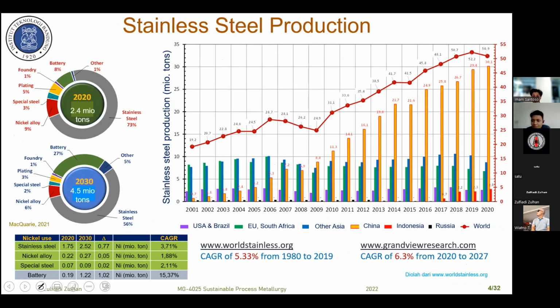If you see the stainless steel production, because most of nickel is used for stainless steel, in 2020 around 1.75 million ton of nickel is used for stainless steel. We see the production of stainless steel worldwide. In the other countries, for example in US, in Brazil, European Union, including South Africa and other Asia, including also Russia, the production is more or less not much changed. It's stable. For example, here in US is around, how much is it? 2 to 3 million ton per year. But a huge increase of production you can see in China. Here it is with the orange color.